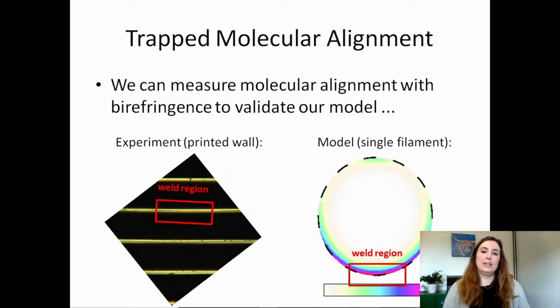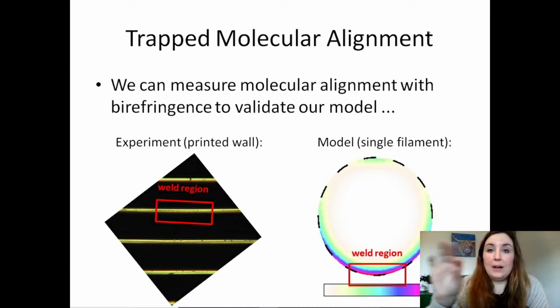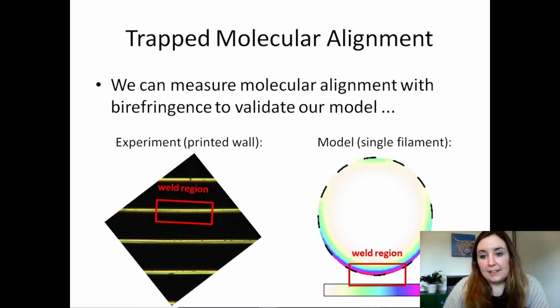What we can do is measure some molecular alignment with what's called a birefringence method. So this is an experiment. It's a printed wall of filaments, so filaments stacked up in the vertical direction, and where there is bright light, that tells us the molecules are aligned, and where there's darkness, that tells us our molecules are kind of randomly coiled up. So what we see is that we get all this molecular alignment really localized to the weld regions between our printed filaments. And that's exactly what our mathematical model is predicting, that we're getting this localized molecular alignment in this region near to the edge of each filament.